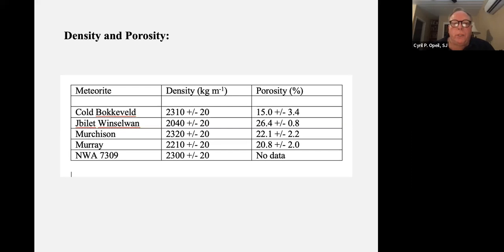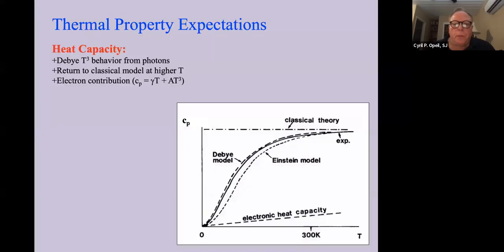Just want to mention that for these samples, Bokkeveld and all the rest here, we measured the density. This has all been done by Archimedes' method after the samples came out of the machine. Looking at the porosity measurements, you can see that the porosity is fairly high. So these are not terribly dense materials; we get to see that there are a lot of holes here, typical for CM2s.